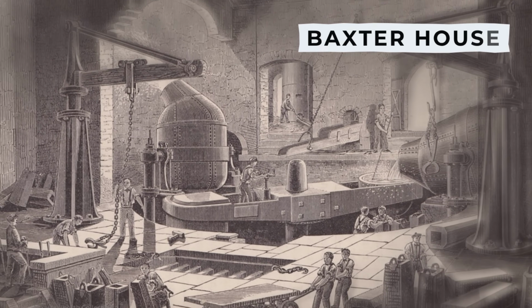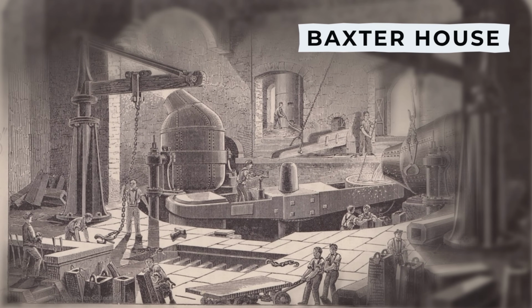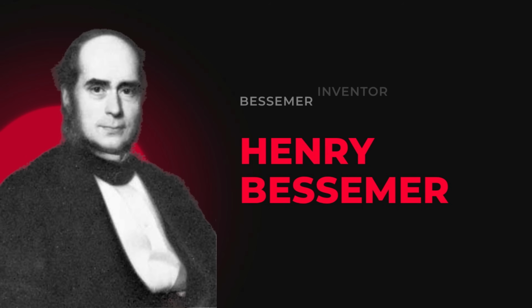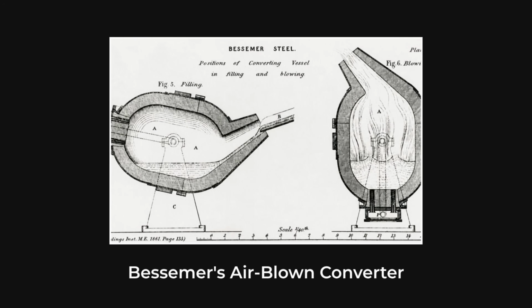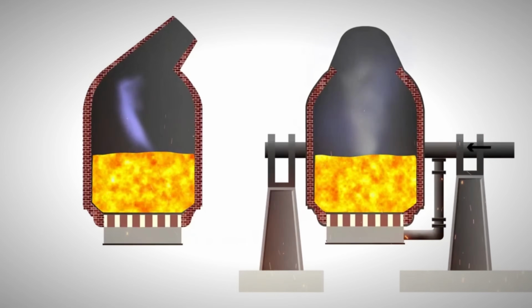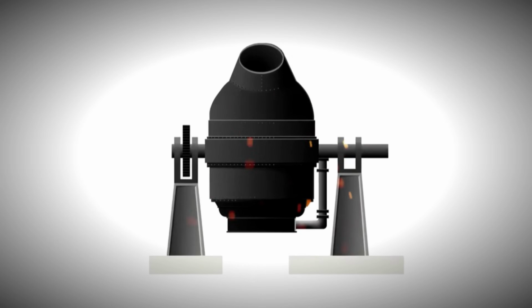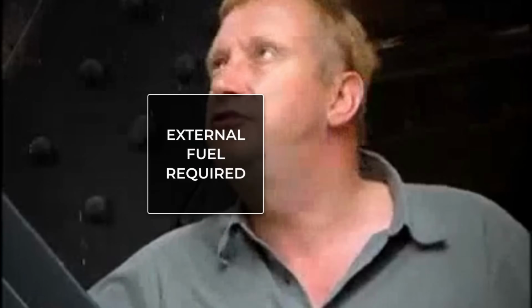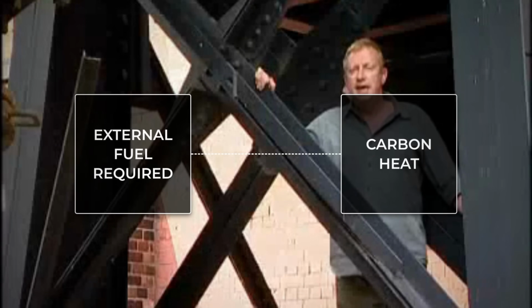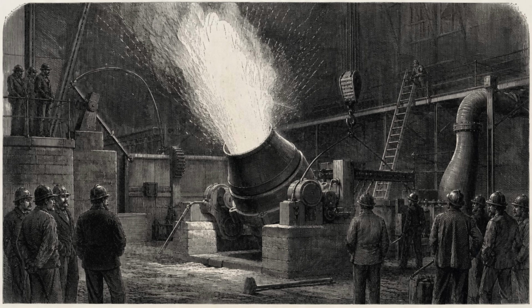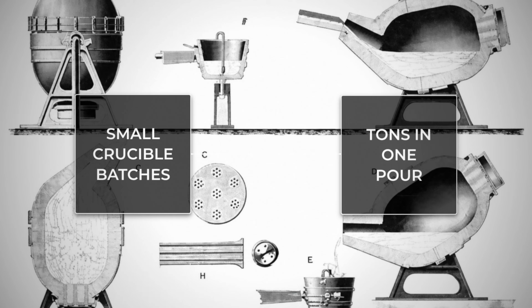While he was in London, he attended a demonstration at Baxter House, where an inventor named Henry Bessemer was showing off a process that sounded like alchemy. Bessemer's idea was to blow cold air straight through molten pig iron. The carbon in the iron would catch fire and burn off, and the burning carbon itself would generate enough heat to keep the whole mass liquid without any external fuel at all. 20 minutes of roaring white flame, and you had steel. Not the tiny crucible batches that blacksmiths had made for centuries, but tons of it, in a single pour.